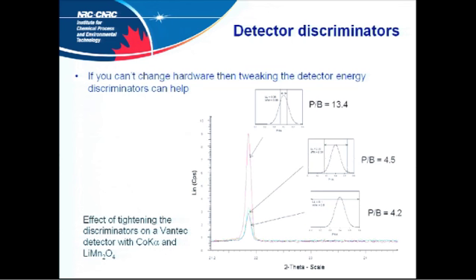If you look in your configurations, detectors have what they call discriminators. This is basically the electronics deciding which part of the energy spectrum it's going to count and which part it's going to effectively ignore. Here we've got the effect of tightening the discriminators with cobalt radiation on this lithium manganese spinel again. If you have the discriminator effectively wide open, you're just taking the whole of your peak and all the background that's coming with it. Peak to background is about 4.2, which is pretty horrible.